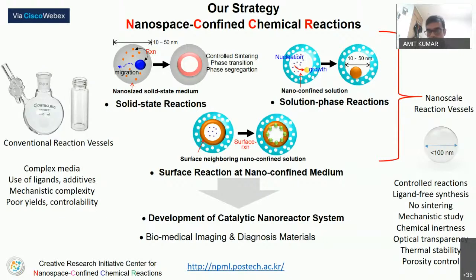Then we subject them to various conditions. In solid state reaction conditions, we expose them to a gaseous environment and heat them to very high temperatures, and we see many novel transformations which can generate various morphologies of nanocrystals. Also, with hollow silica nanoparticles, we can perform seed-mediated synthesis within nano-confined media, and we can also perform surface galvanic replacement chemistry and other chemistries within the nano-sized media.